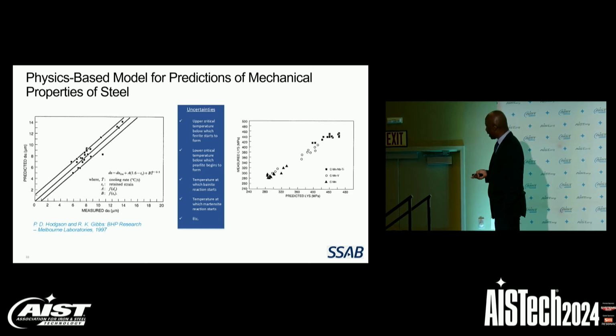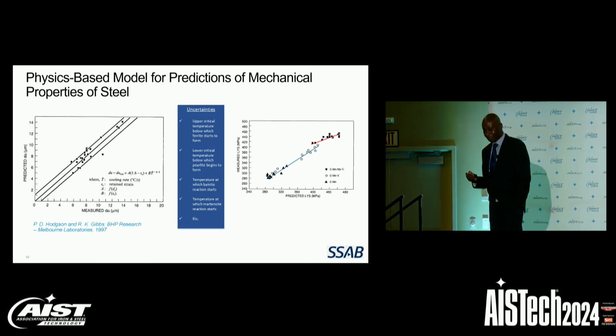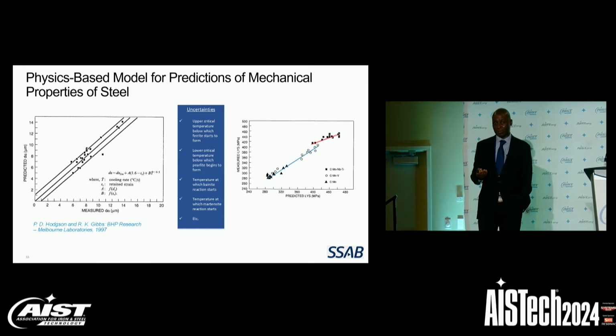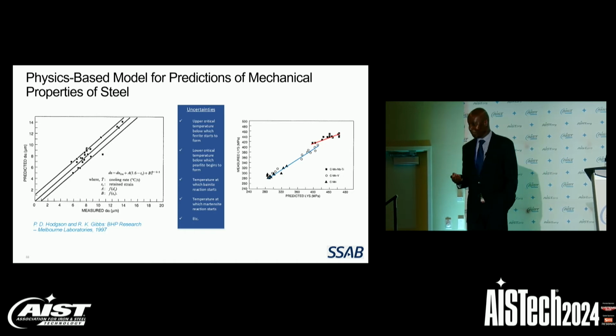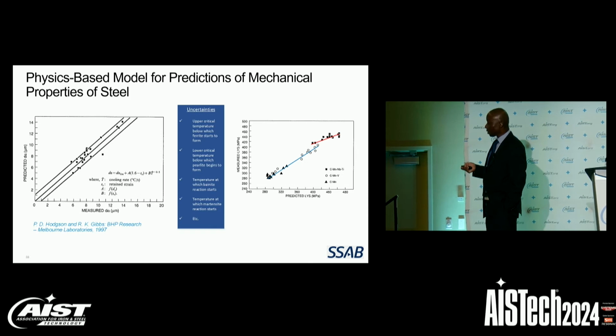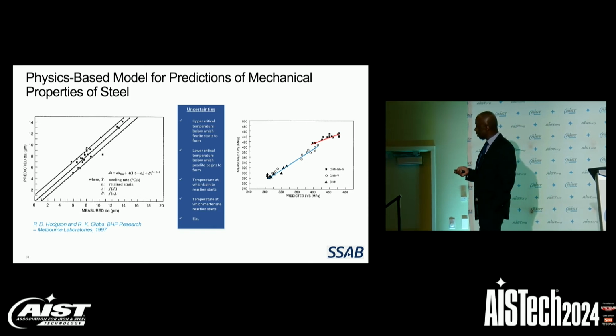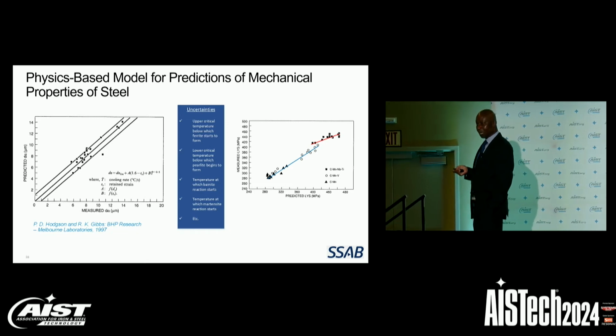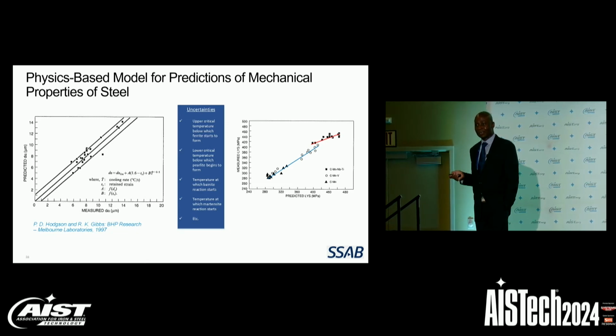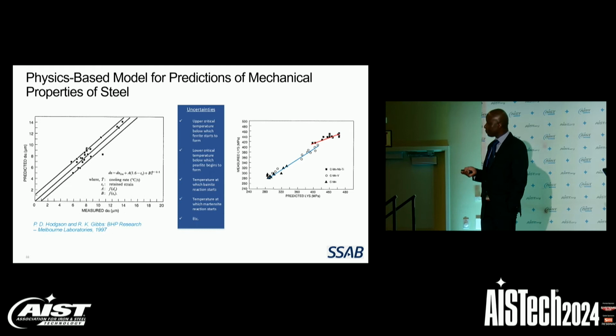So when they applied their model to predict the yield strength for different carbon manganese steel, they found that the prediction is pretty accurate for ordinary carbon manganese steel. Now, when they use the model to predict for carbon manganese steel that has multiple microalloying elements, the accuracy declines significantly.